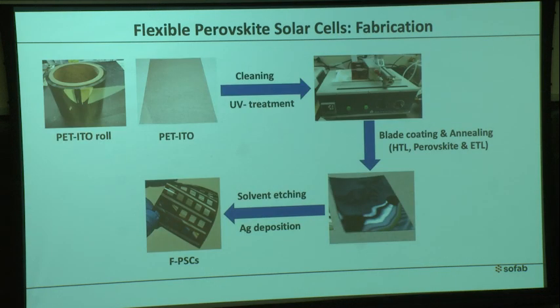After that, we fabricated a flexible perovskite solar cell, trying to translate exactly the same thing we did previously on glass to plastic. This is our schematic: this is the roll of plastic. We clean it, and then deposit all the layers the same way — HTL, perovskite, and ETL via blade coating. The stack contains HTL deposited by blade coating, perovskite deposited by blade coating, and ETL tin oxide.